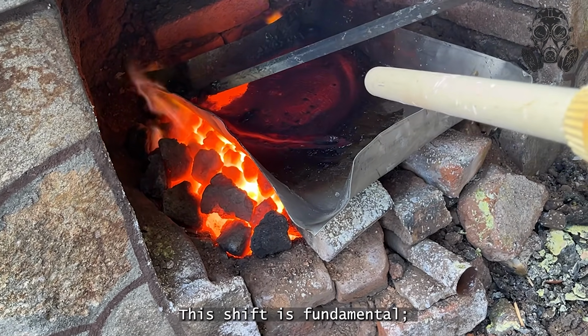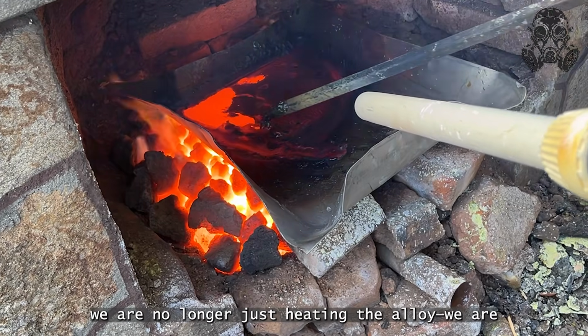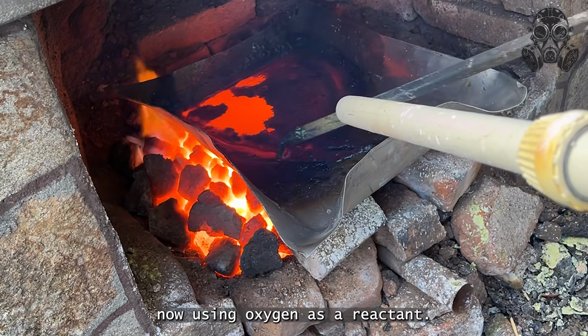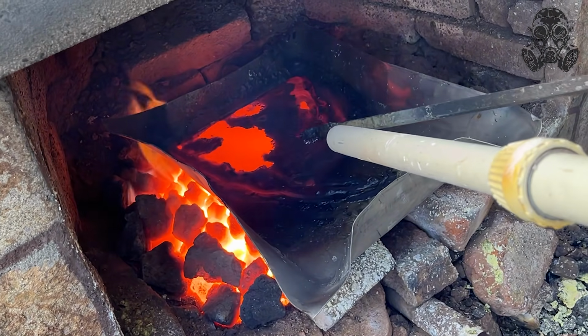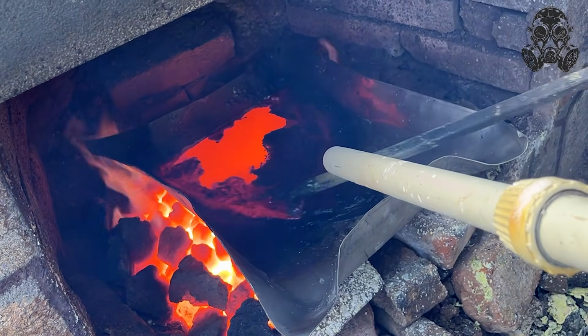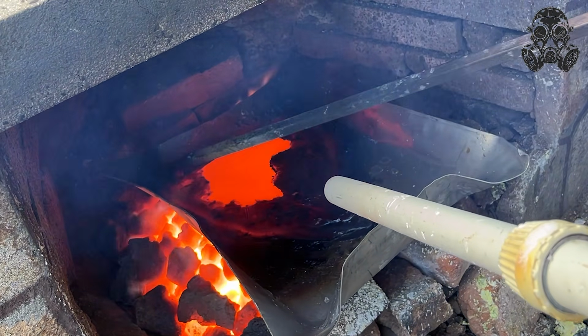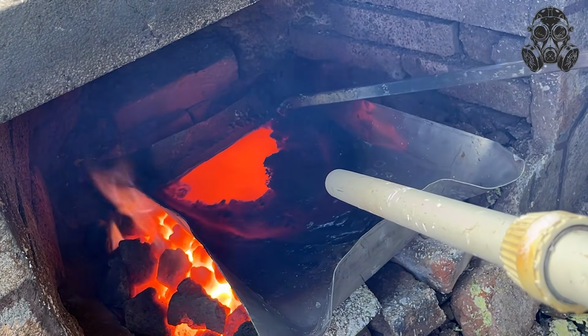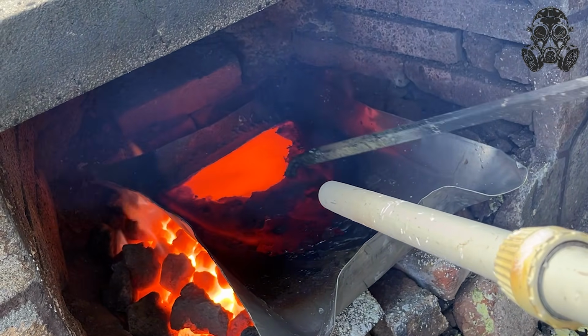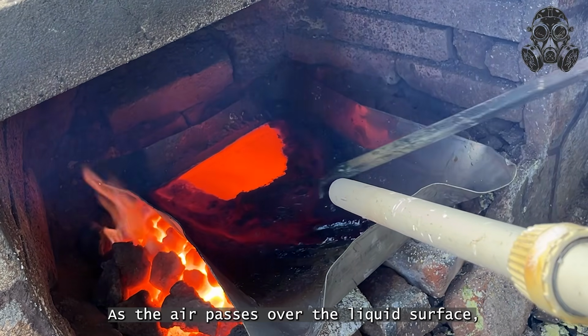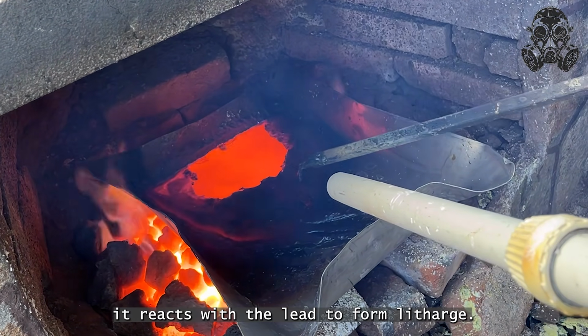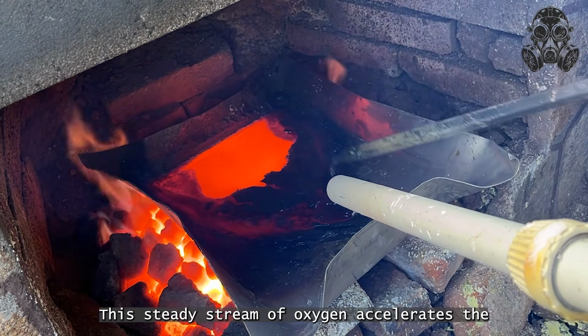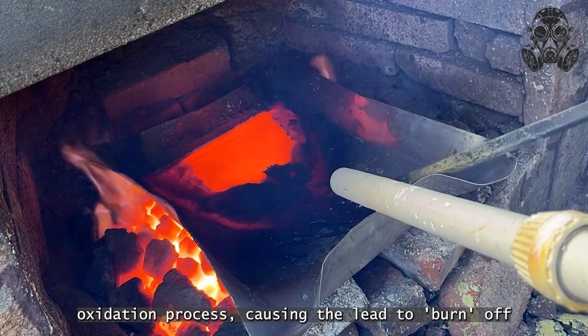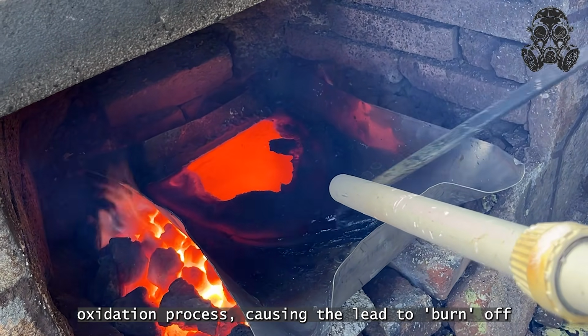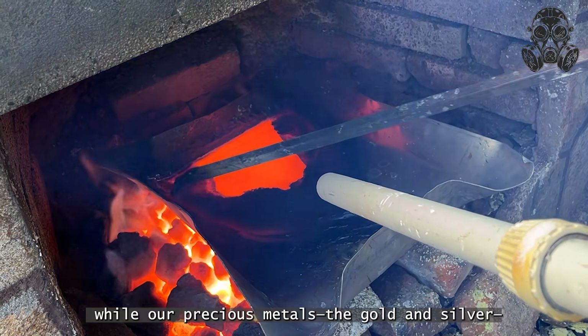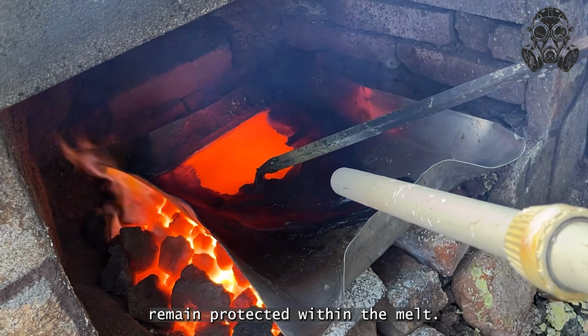This shift is fundamental. We are no longer just heating the alloy. We are now using oxygen as a reactant. As the air passes over the liquid surface, it reacts with the lead to form litharge. This steady stream of oxygen accelerates the oxidation process, causing the lead to burn off while our precious metals, the gold and silver, remain protected within the melt.